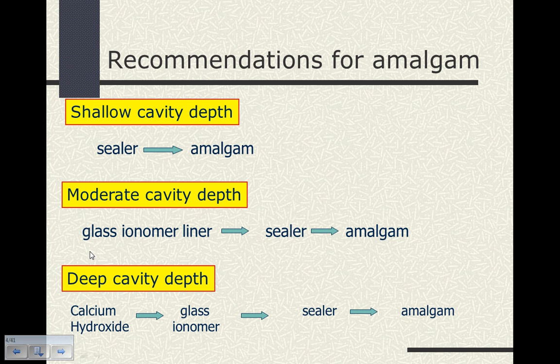So let's look at the recommendations for liners, sealers, bases for different types of depth cavity preparations. And we're first going to look at amalgam. For a shallow cavity preparation, we're only going to use a sealer, typically a cavity varnish, and then the placement of amalgam. Those are preparations half a millimeter into the dentin. For moderate cavity depths, those that are within 1 to 2 millimeters of the pulp itself, and we note that by a radiograph, we place a glass ionomer liner, Vitrebond, then our sealer, our cavity varnish, and then amalgam. For deep cavity preparations, we're going to use calcium hydroxide in isolated deep areas of the cavity preparation, covered completely as a liner, the glass ionomer, followed by our barrier cavity varnish, and then our amalgam.